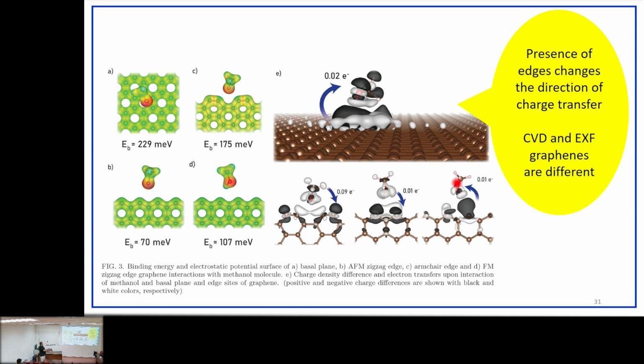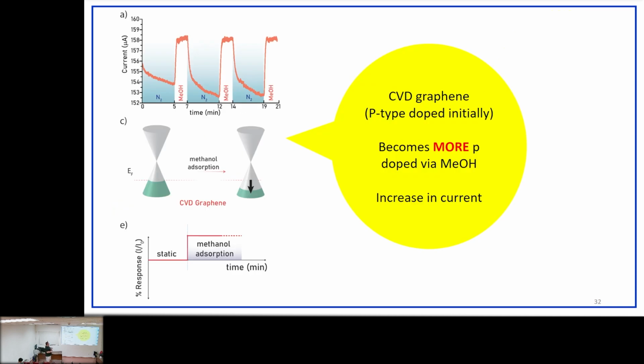But you see, if you have exfoliated graphene, you have lots of edges, lots of edge states. So they will play a role, and you see what's the dominant effect? The dominant effect is charge transfer from methanol to the exfoliated graphene. But if you are dealing with CVD graphene, charge transfer will happen just from the surface to the methanol molecule. Okay? So now we understand why they behave in different ways.